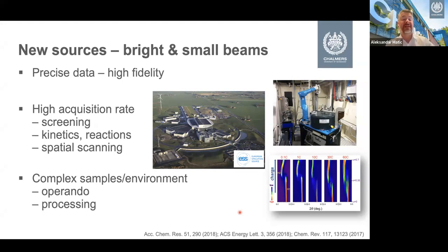We can use this for high fidelity. But we can also use it for high acquisition rate, which means we can now go towards screening our materials, which I think has been done much more in other fields. If you go, for instance, to protein crystallography and so on, where you use robotic systems for sample change, and you can go through a large range of materials and see which one is best. But we can also follow kinetics, we can follow chemical reactions, or we can use the high acquisition rate to actually do a spatial scanning over our device and use a large range there. And of course, we can go to complex sample environments to do operando characterization. So to look at real materials under real conditions in real time.